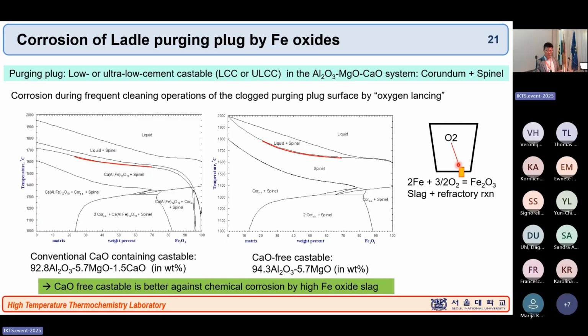And then while they were doing this, they found out that at the end of the process, this oxygen starts to make a chemical reaction with the remaining slag, which is typically Fe2O3, we can assume in that way, and then this Fe2O3 and this porous plug start making a chemical reaction. So they want to know whether this CaO addition has some impact or not. So we drew the phase diagram, like here is this refractory material on this corner of the x-axis, and on this corner we have Fe2O3.